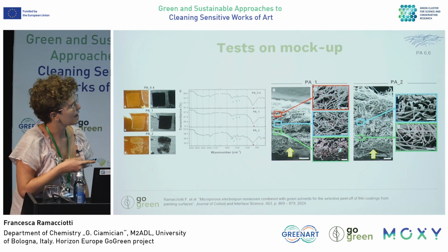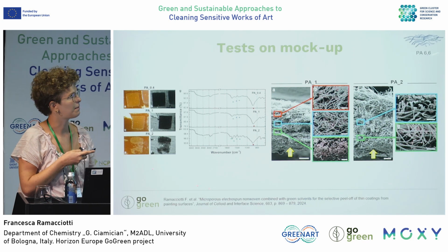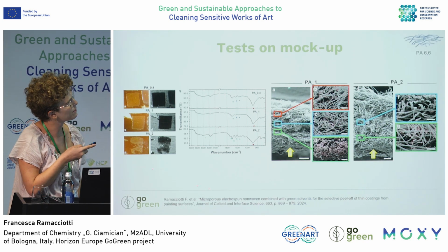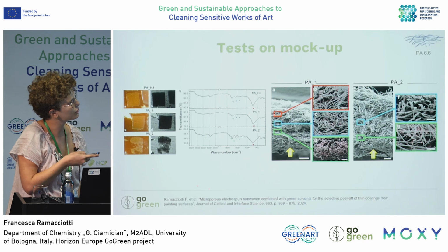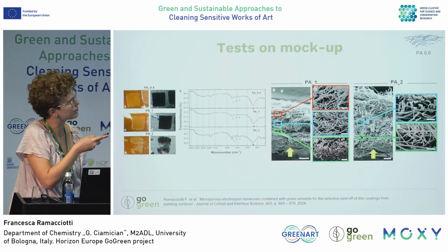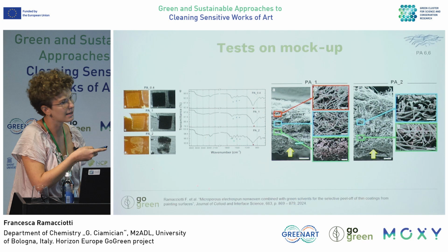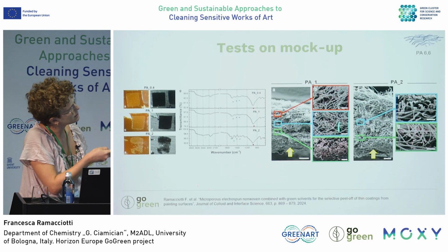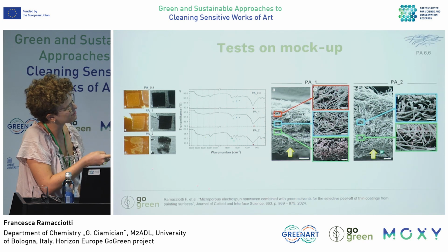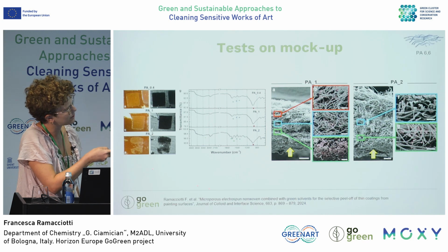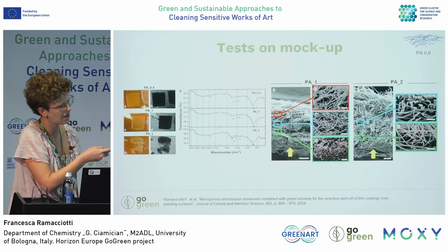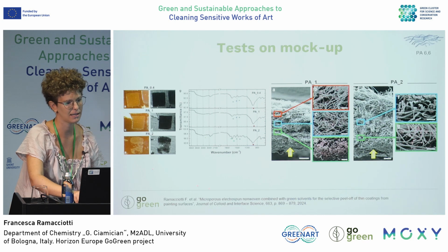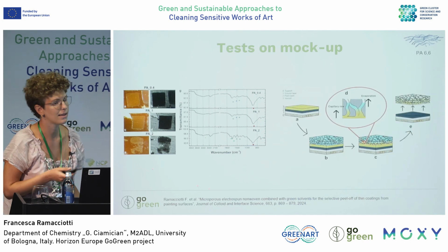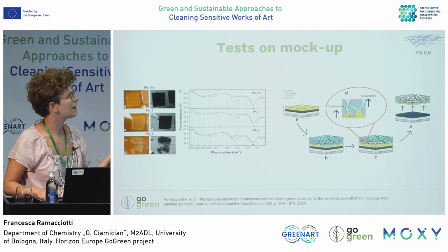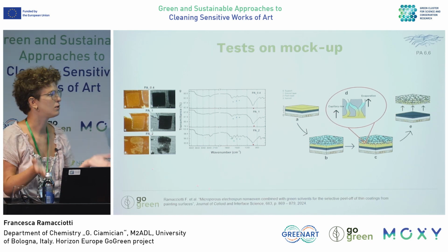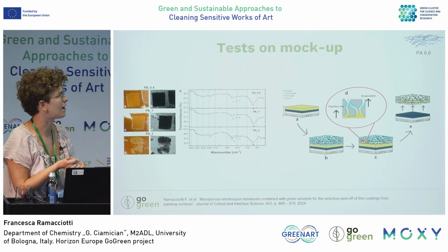With SEM on sections of the mats after application, we observed that when we have small pores, we have a distribution of the varnish within the entire section of our mat. This is the side in contact with the painting. While when we have big pore sizes, we have still the varnish within the section, but confined in the lower part. So this and other studies led us to identify the capillary rise as the main mechanism leading to the cleaning. So the smaller the pores, the higher the capillary rise.